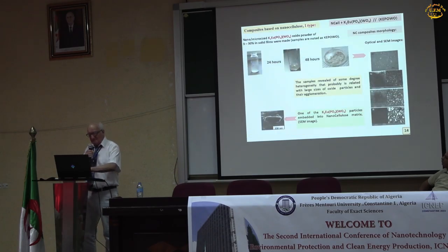Here you see some other type of composite based on nanocellulose, the stage of the preparation. These are thick films, one millimeter and more. The sample reveals some degree of heterogeneity that is probably related to the large sizes of oxide particles and their agglomeration. At the bottom you see one of the particles embedded into the nanocellulose matrix.